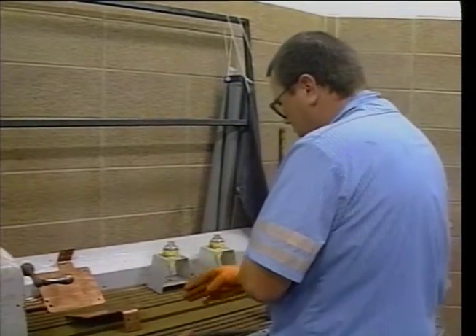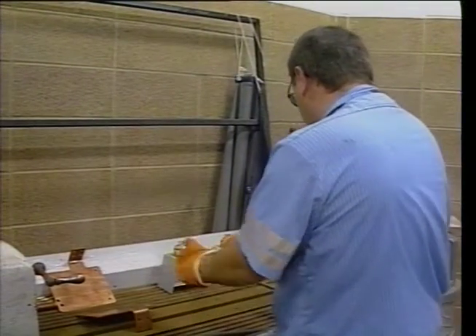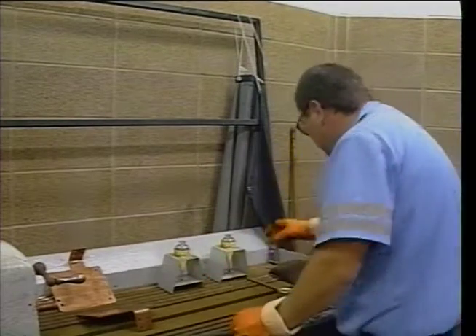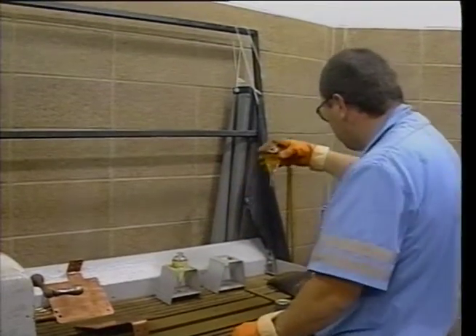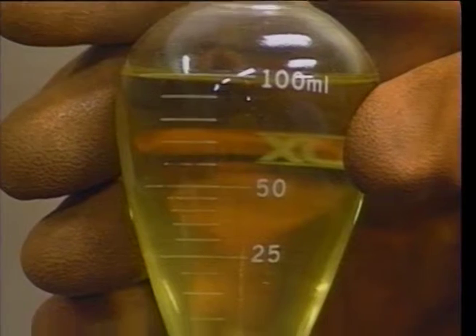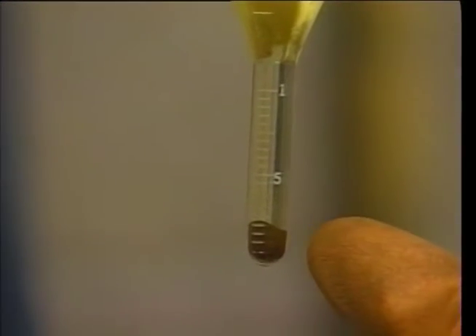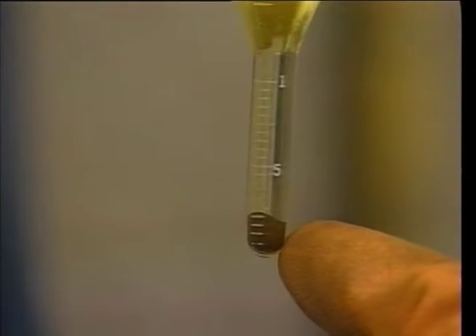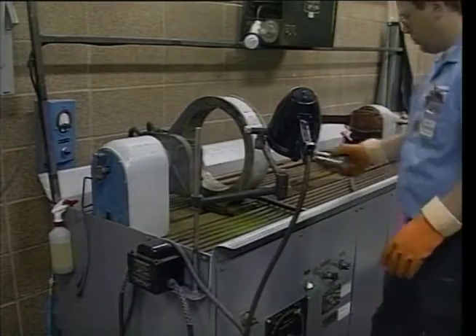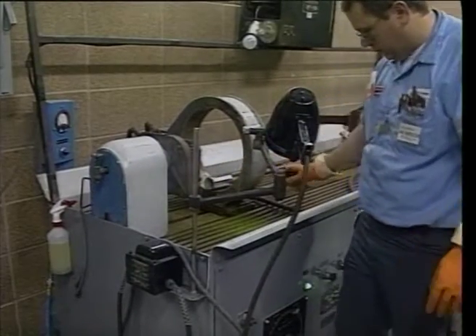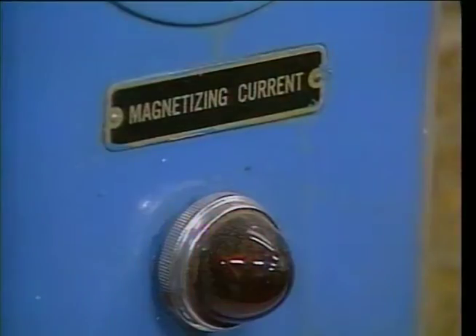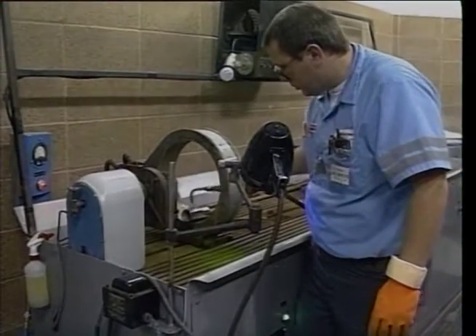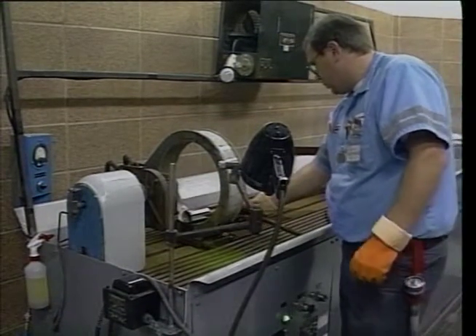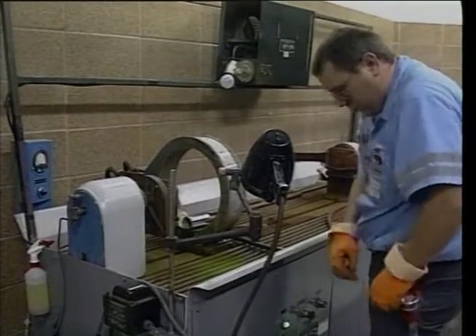The startup includes agitation of the mag particle suspension liquid, as well as checking of the particle concentration. Since the system recirculates, particle content can be depleted. The part being inspected, in this case a high-strength steel fuse pin, is magnetized in the high-energy field of the unit and flushed with the mag particle solution.